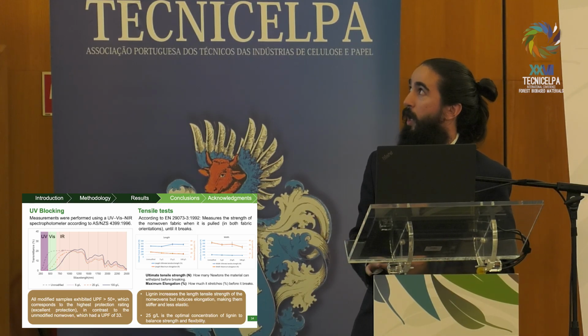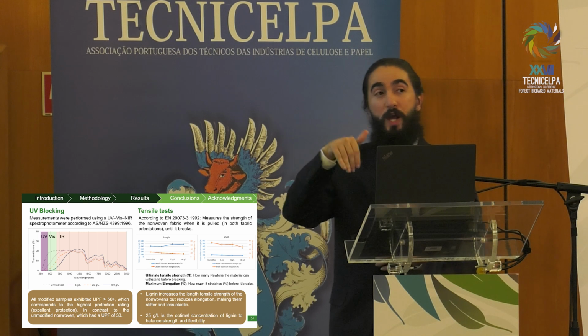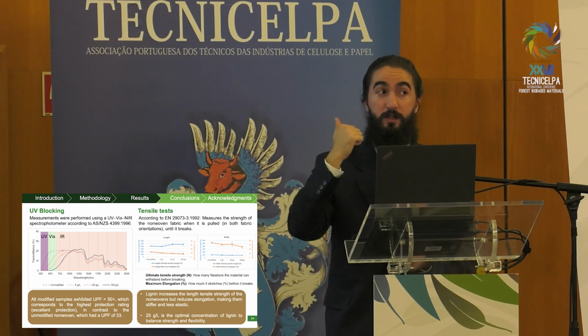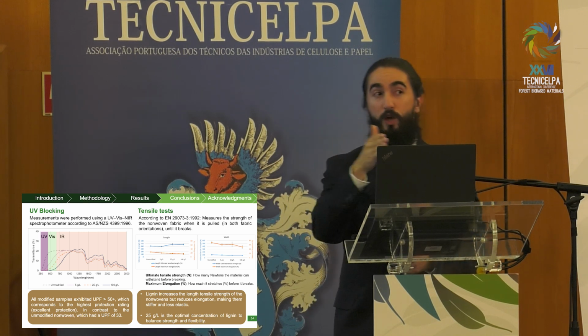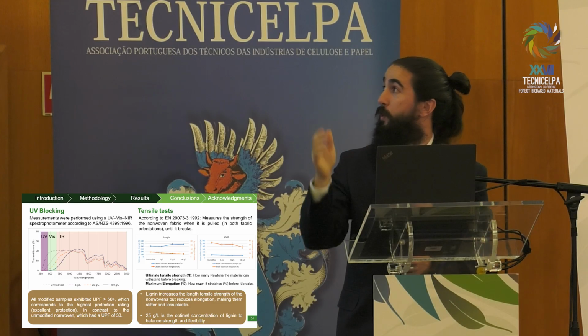We also did some tensile strength tests here, according to this norm, which basically assessed the ultimate tensile strength and maximum elongation in the machine direction of the nonwoven. Once again, we did needle punch nonwovens, and also in the cross direction, so in the length and in the width.